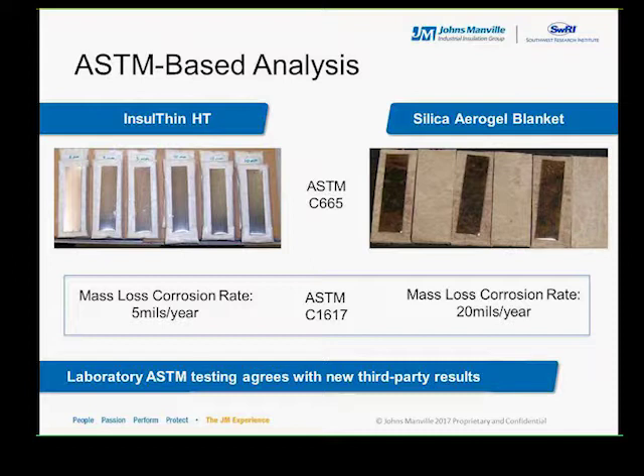So very encouragingly, the results of both the ASTM test methods agree with what we've seen and what we just described in the NACE TG516 protocol. And you can see that the silica aerogel blanket has more visible corrosion products on the surface compared to the Insulthin HT sample using the ASTM C665, and that the mass loss corrosion rate in C1617 is 4 times higher in the silica aerogel blanket compared to the Insulthin.